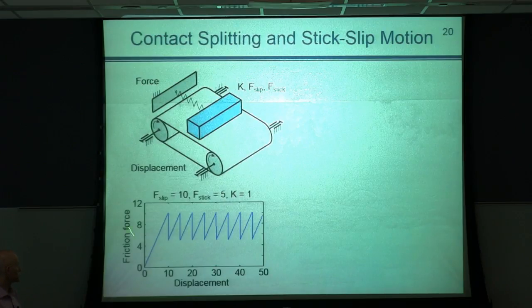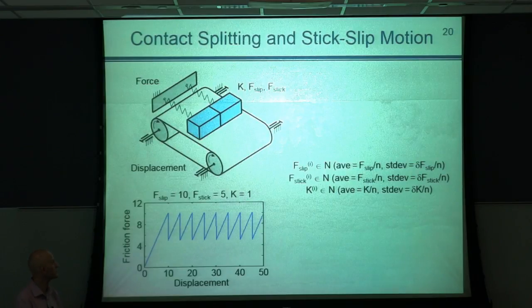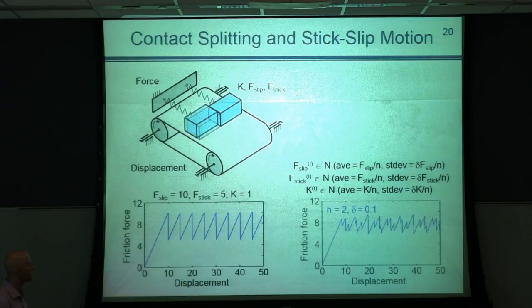So these were the initial conditions, and we started to split this block into a large number of small structures, while the total stiffness and forces in sum remain the same. The interesting thing: when we split a large surface into two smaller surfaces, if the properties, the friction and the stiffness, in both bodies have the same values, then the friction force behaves in absolutely the same way. However, if we introduce some statistical variance in all three properties, then differences start to be seen. Friction force, shown as a function of displacement, has some fluctuations that resemble the more natural behavior of surfaces that come in contact.